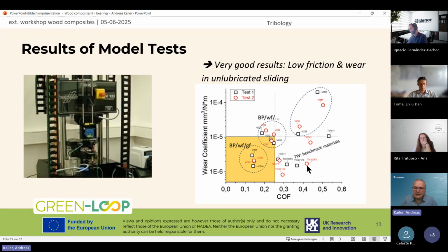On the right side, you can see here at larger friction coefficients benchmark materials. We have got some materials composed of polyamide filled with fibers and PTFE as friction modifiers, which is a very common composition for tribological applications. You can see here the wear coefficients are in the same range, while the friction coefficients of these materials are considerably higher. So very good for two material types in this first batches.